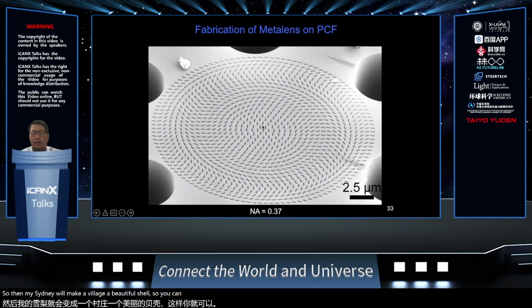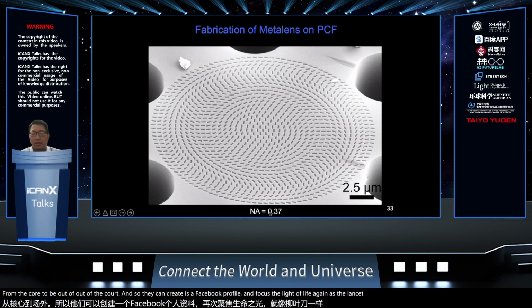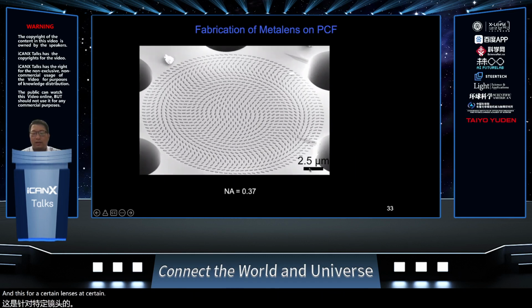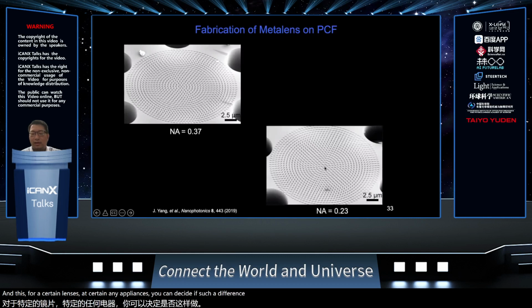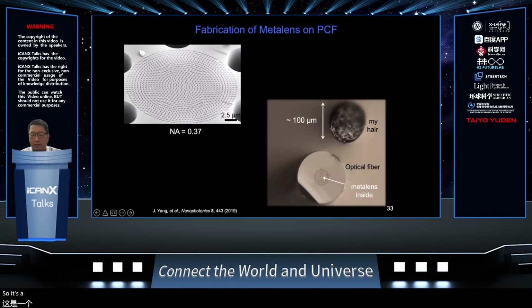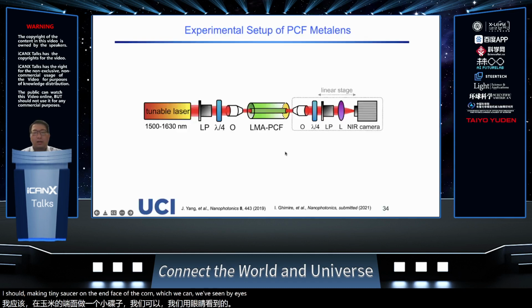So you can see that inside the core, you're gradually rotating the structure from the core to the outer core, and so they can create this phase profile to focus the light as a lens. And this is for a certain lens, a certain NA of lens. You can decide the structure for different NA to focus the light by just changing the rotational distribution. So just keep in mind again, this is an optical fiber. It's like my hair. We're actually making tiny structures on the end face of the core, which we can't really see by eye. But you're actually able to measure this kind of lensing property.